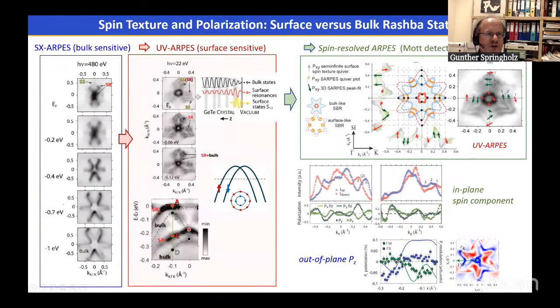Now, we also measured the spin texture associated with the Rashba effect. The problem with that is that soft X-ray ARPES is bulk sensitive, but the intensity is very low, so it is not possible to do spin-resolved measurements and measure the spin polarization of the emitted photoelectrons. For that, you have to go to UV, so-called UV ARPES, where the photoelectrons are excited with UV light in the 10 to a few 10 electron volt range.